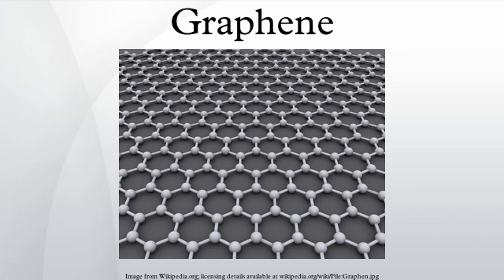The weak van der Waals force that provides the cohesion of multi-layer graphene stacks does not always affect the electronic properties of the individual layers. That is, while the electronic properties of certain multi-layered epitaxial graphenes are identical to that of a single layer, in other cases the properties are affected, as they are in bulk graphite. This effect is well understood theoretically and is related to the symmetry of the interlayer interactions. Epitaxial graphene on SiC can be patterned using standard microelectronics methods. A band gap can be created and tuned by laser irradiation.